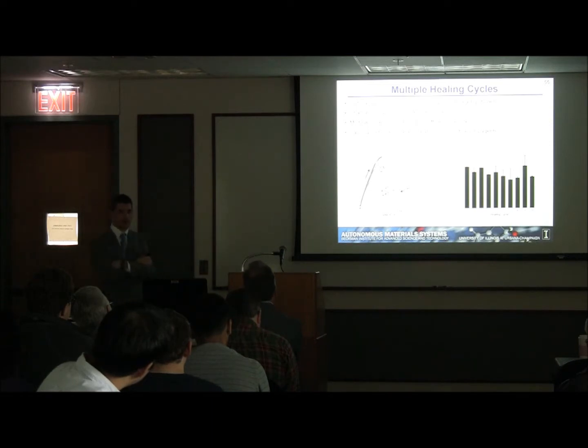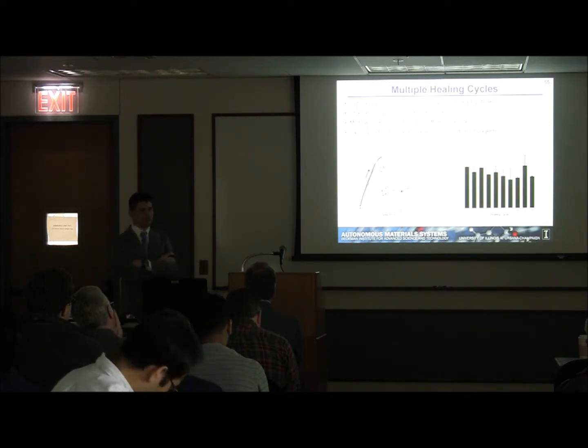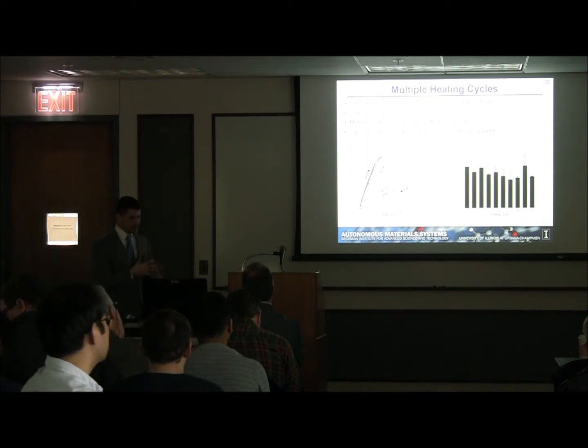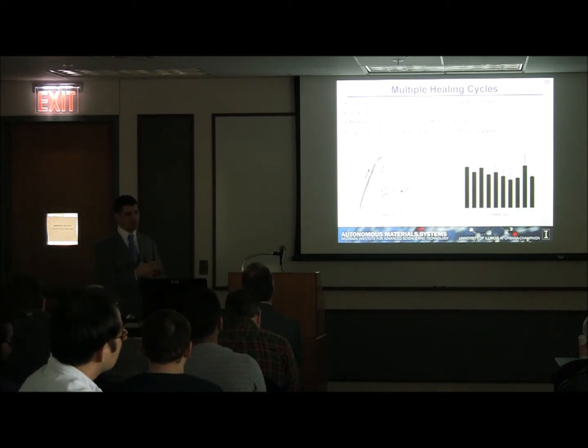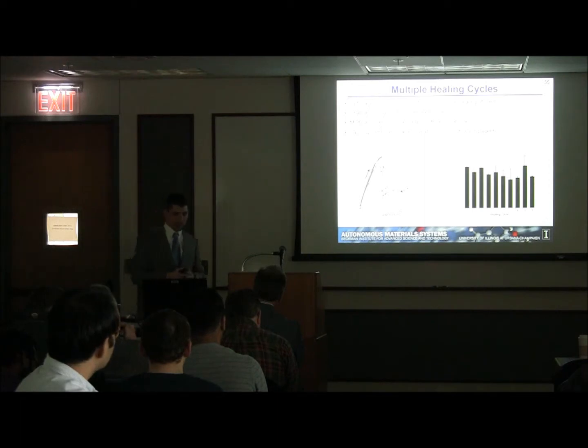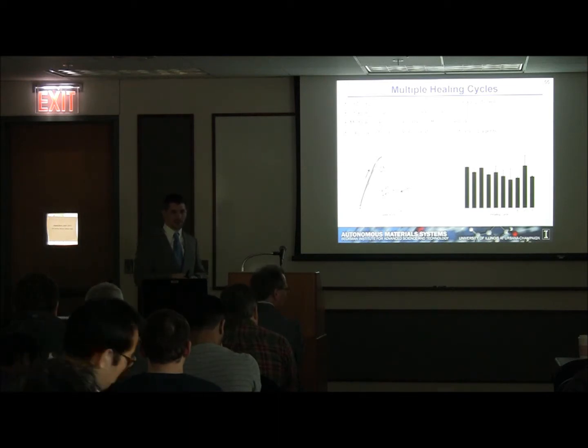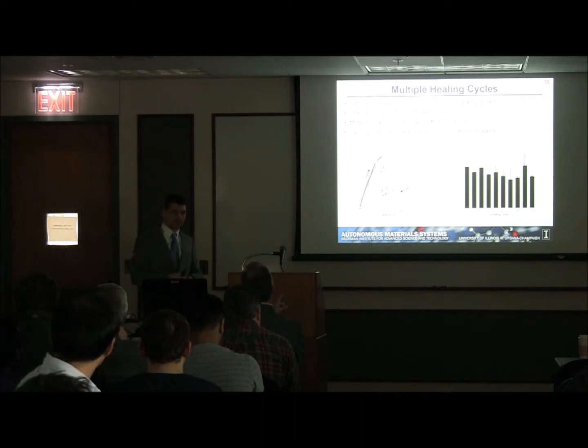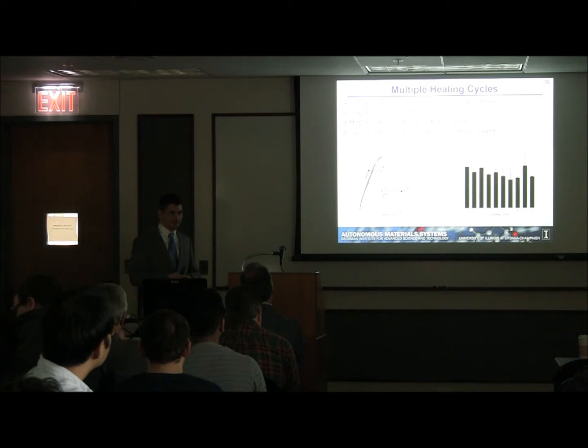We did look at Raman microscopy of the cross-section, and we looked at the mix ratio at discrete points in the cross-section. We did see that the mixing ratio of the components near where the channels were located was lower than the mixing performance far from the channels. So there may be healing agent injection, or there may just be worse mixing near the site of egress from the channels. There could be a lot of things that cause reduction. We did look at both. Yeah, it occurs in both.